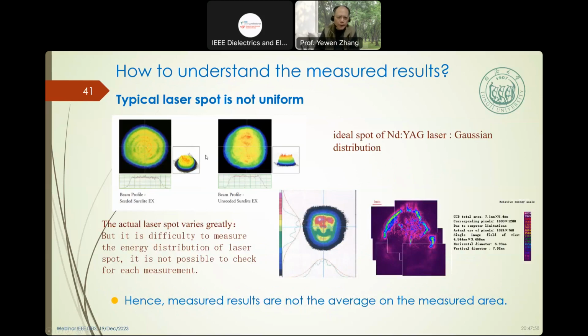So consider the measuring laser. The typical laser spot is not uniform. This one is not our laser, it is typical from the manufacturer. Even this laser is not uniform, something like this. Our laser is a more ideal spot, with a Gaussian distribution. So our laser is more uniform. Hence the measurement result is not uniform, not the average, and there is a measurement error.